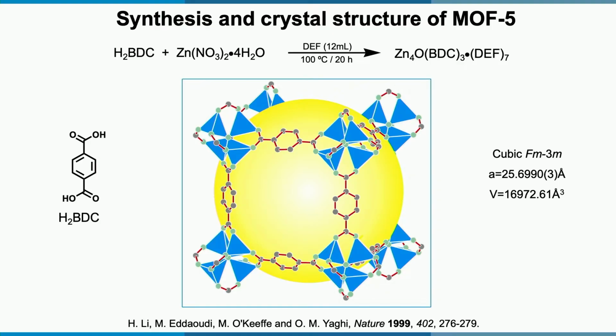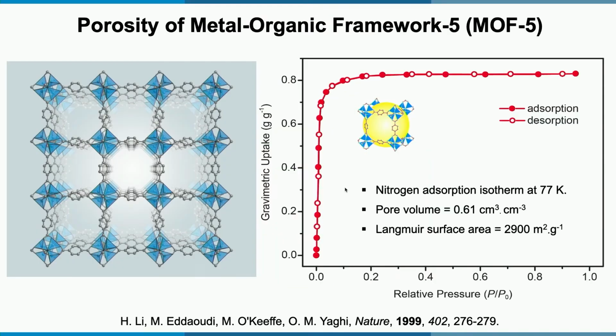But here you have now a three-dimensional structure. It's not layered, but it extends in three dimensions. And this is what it would look like. We use the yellow ball to indicate the space within which you could trap things. And this is the isotherm. This isotherm shows that nitrogen can go into the pores and out of the pores in open circles in the same way.